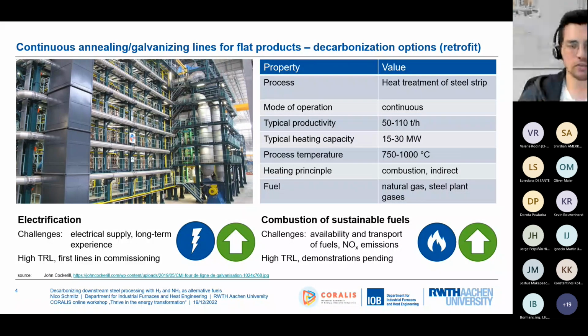If we now go more downstream, for the heat treatment of flat steel, we have the continuous annealing or galvanizing lines. The process taking place there is a heat treatment, so defined heating and defined cooling of the product in continuous operation. So you see the productivity is a bit smaller there, 50 to 110 tons per hour, with a heating capacity of 15 to 30 megawatts. And the process temperatures are also lower, between 750 and 1000. 1000 is also an exception, but we are more between 750 and 850 here.